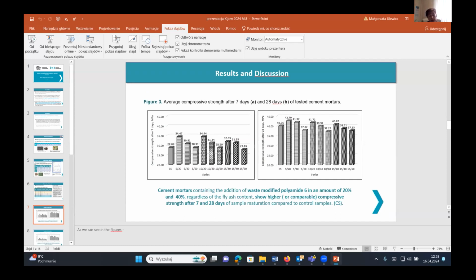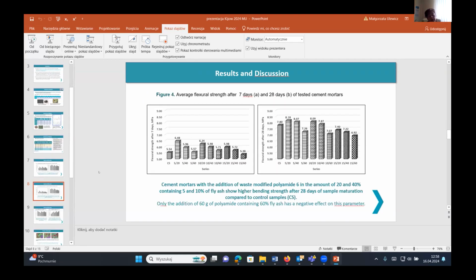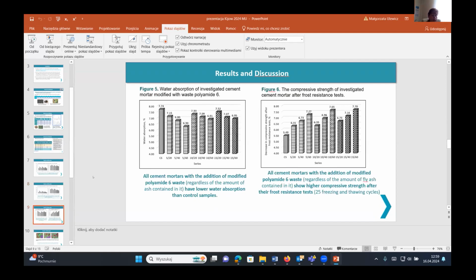This is a recommendation for us to produce in the future. But after 7 days, the properties are similar. Also, there is good flexural strength. Cement mortar with added modified polyamide 6 in an amount of 20 and 40% is good, and has higher flexural strength after 7 and 28 days compared to the control sample. All cement mortars with addition of modified polyamide 6 have lower water absorption than the control sample and higher compressive strength after the frost resistance test of 25 freezing and thawing cycles.